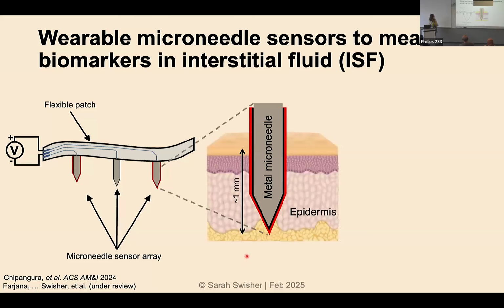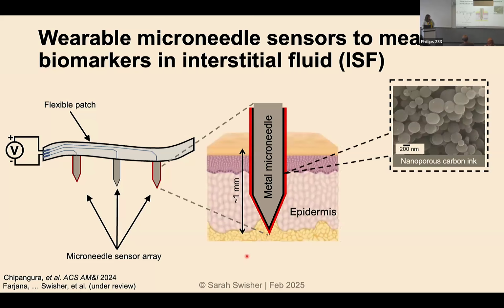The reason for that is because we can put coatings on these microneedles that will make them sensitive to particular biomarkers. Here we're looking at the ion concentration of the interstitial fluid that's in that epidermis. We don't really want to get blood, and we don't really want to hit nerves. So we keep this needle very short and keep it up in the upper layers of the skin.